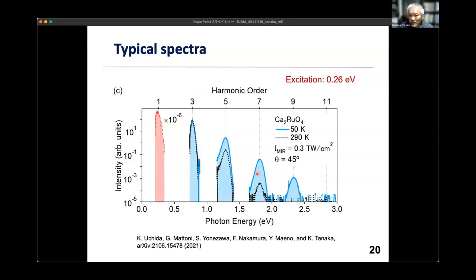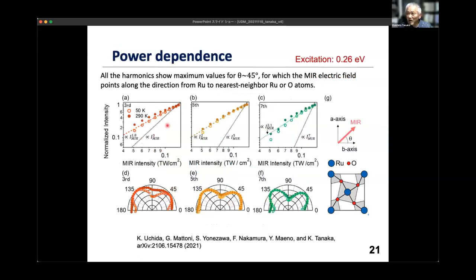So please look at this black dotted curve. This is the room temperature experimental data. If you look at the 3rd order and 5th order, there is almost a 2 orders decrease like this. But if you cool down to 50 Kelvin, the intensity of the higher harmonics increases a lot. We checked the crystal angle dependence and also the power dependence, for all orders, and it is not dependent on the temperature. The intensity shows almost a square dependence like this, which is far from perturbative theory. So the system is in the non-perturbative regime.